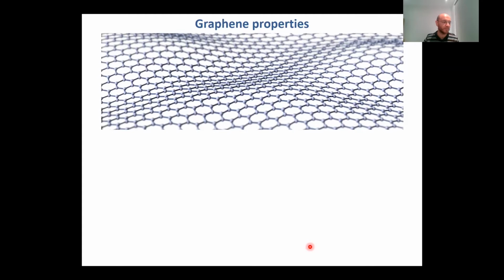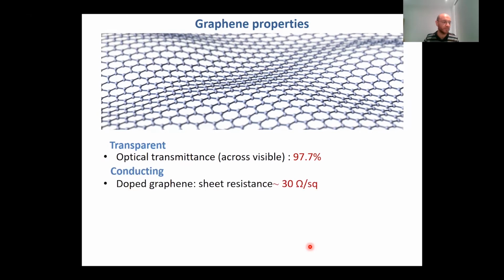But if we look at the properties of graphene, of course, we know that being an atomically thin material, it is highly transparent. Also, with some doping and improvement of the stability of the material, you can achieve sheet resistance down to a few tens of ohms per square. And this is pretty relevant for consistency of conductivity in conducting tracks. And also, it's a pretty stretchable material. And this is very important when you want to make stretchable, highly conformable devices.